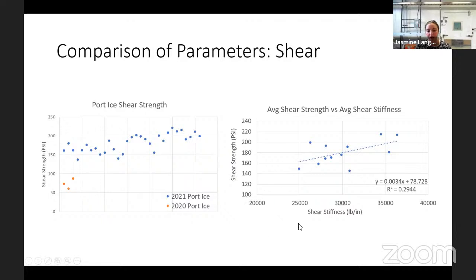And then we also compared the shear strength with the shear stiffness. And again, you have a positive relationship. This one's linear, but not a super strong relationship, with an R squared of only about 0.3.